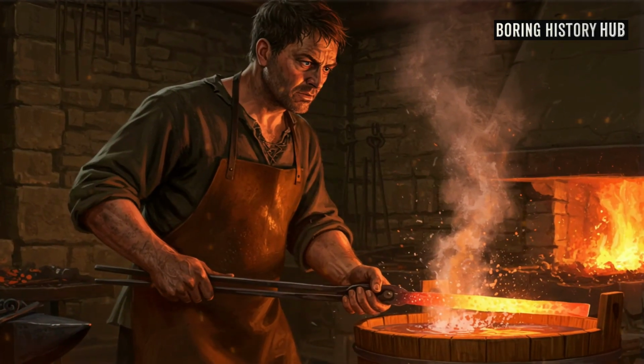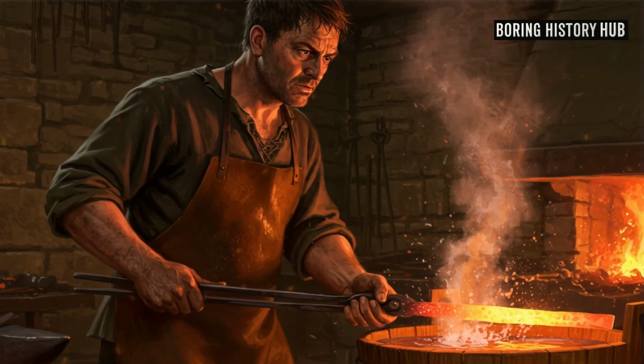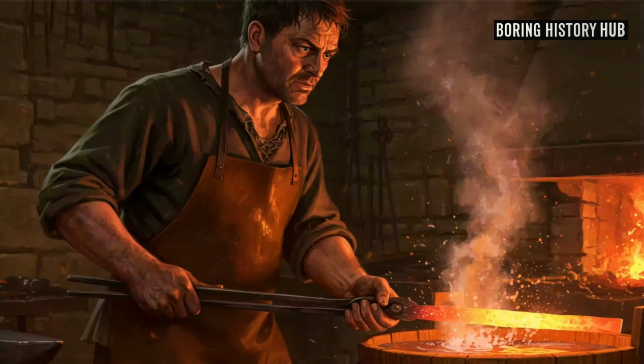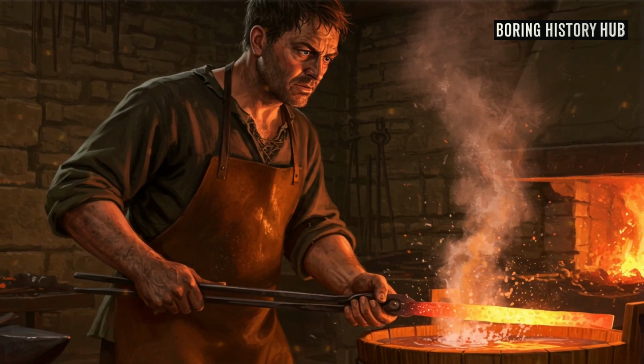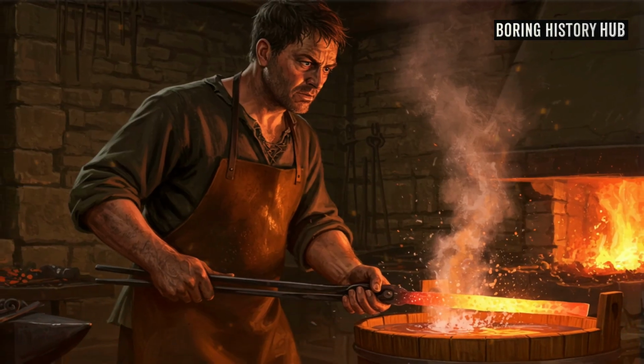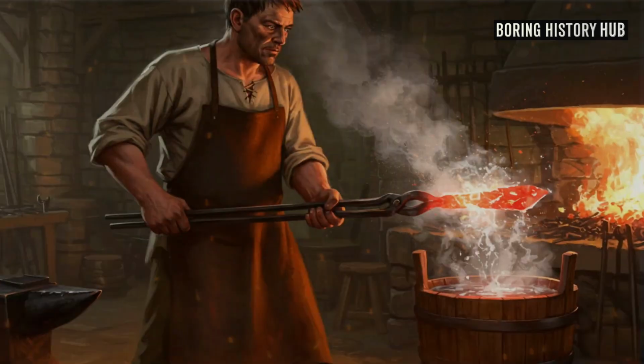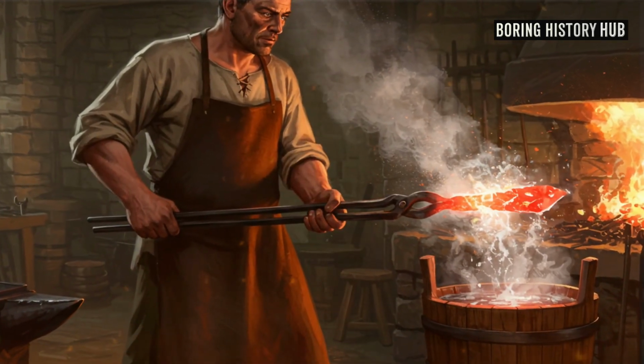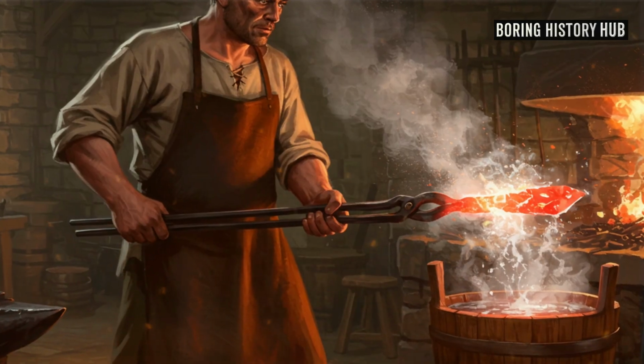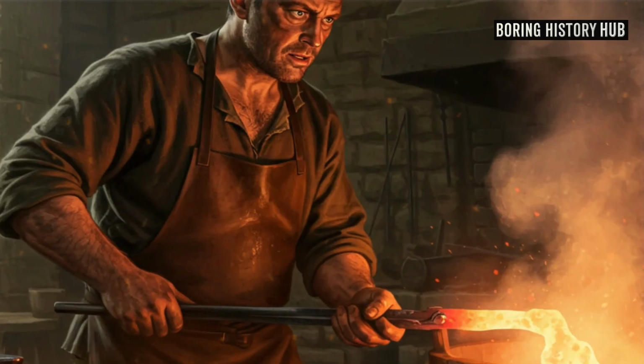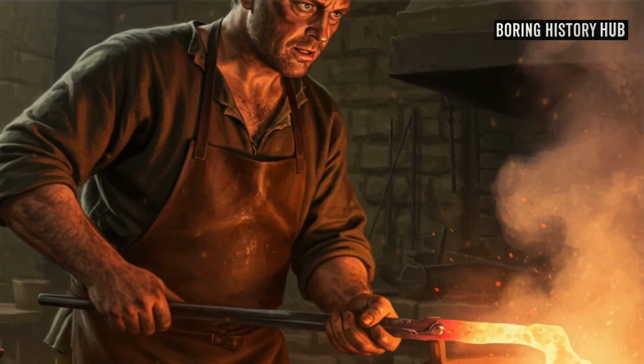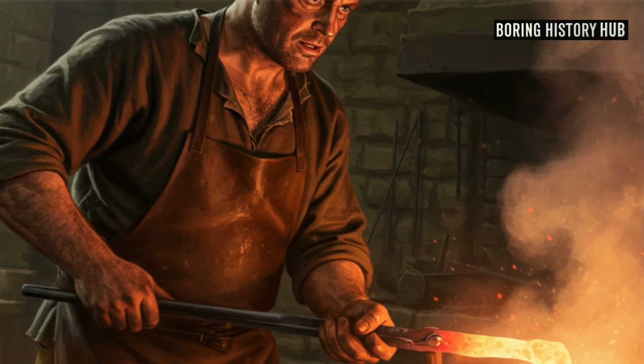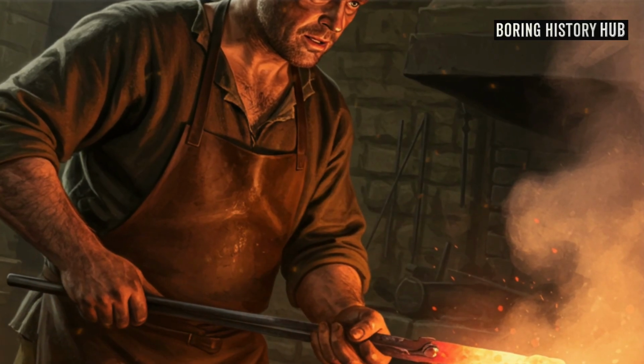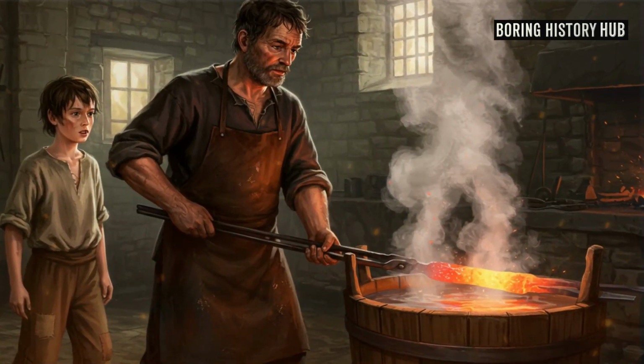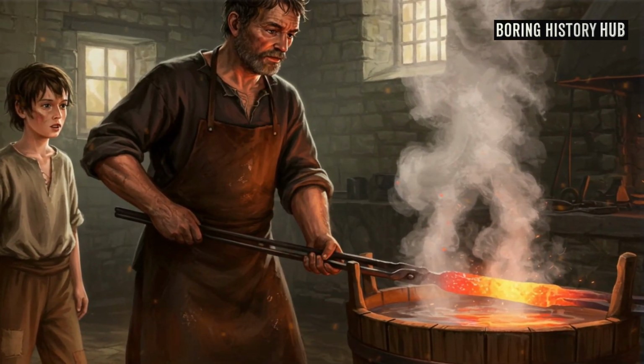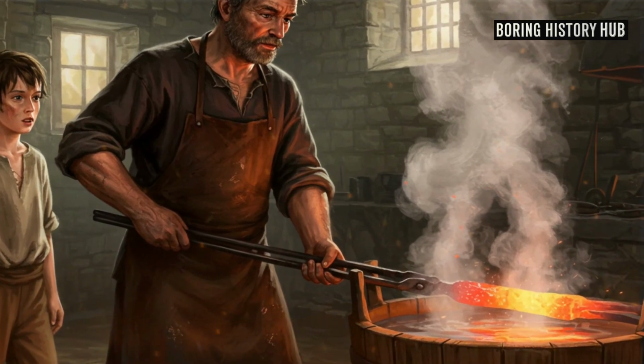The blade needed to be hardened to develop the steel's potential for holding a sharp edge, then tempered to reduce brittleness while maintaining adequate hardness. Edmund heated the blade to a bright cherry red, then quickly quenched it in a tub of water. The sudden cooling locked the steel's crystal structure into a very hard but brittle condition. Steam hissed and bubbled violently as the hot metal hit the water, filling the smithy with a cloud of vapor.